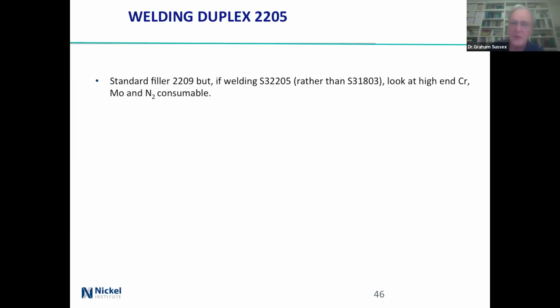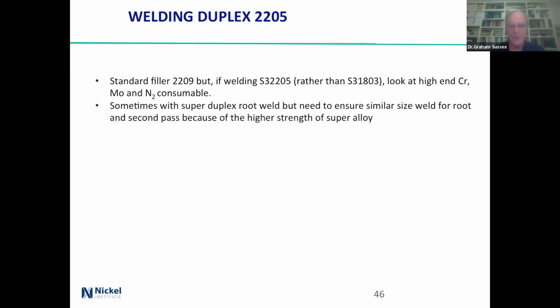For 2205, the standard filler is 2209, but if you're welding 32205 rather than 31803, so you're up in the top end of the range, then look at the high-end chromium and moly. So you do have more corrosion resistance in the system, but 2209 has just got 22 chrome, and maybe you need to be looking at a bit more nitrogen.